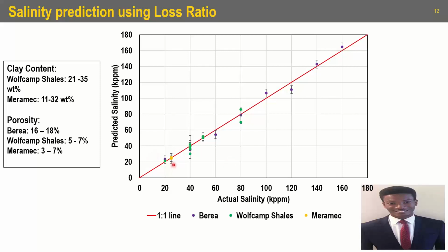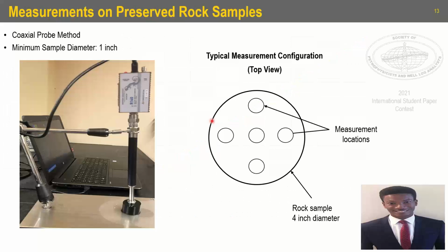And for our Meramec samples, the various ones that were imbibed, or saturated rather, in 25,000 ppm, we see that they fall pretty much on the one-to-one line. So that helps us validate that this seems to be a really good method in predicting salinity. To use this in other cases, we then go ahead to make measurements on preserved rock samples.